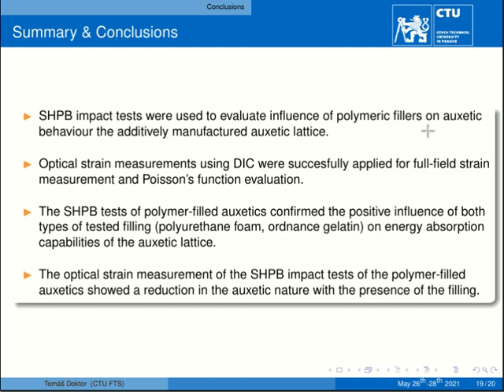The SHPB test of polymer-filled auxetics confirmed the positive influence of both types of tested filling at dynamic strain rates. On the other hand, the optical measurement of the strain at the surface of the samples showed a slight suppression of the auxetic nature of the tested lattices.